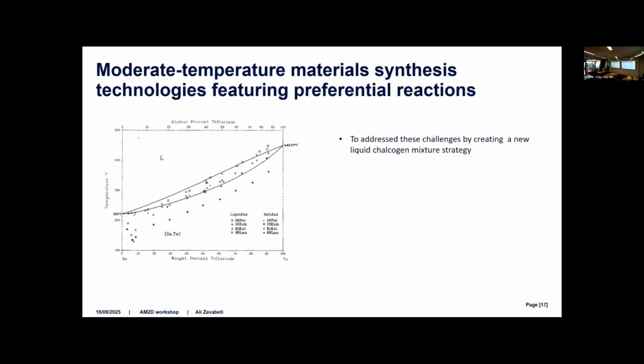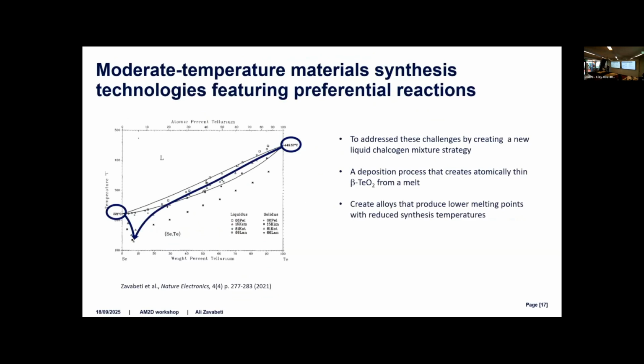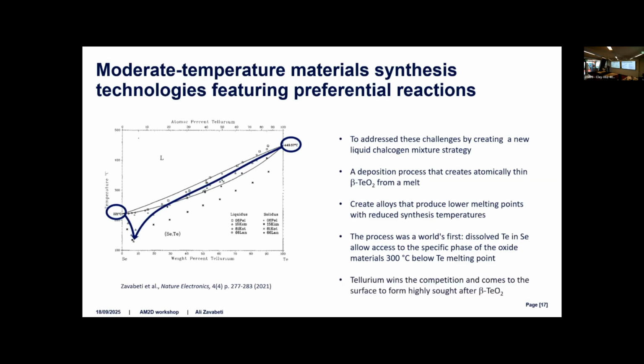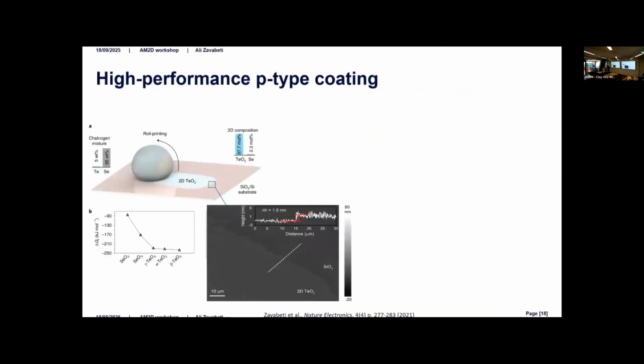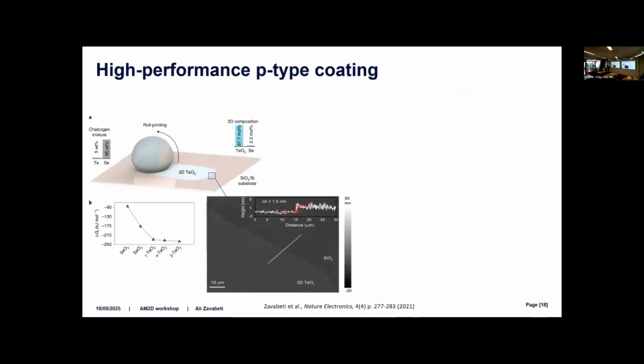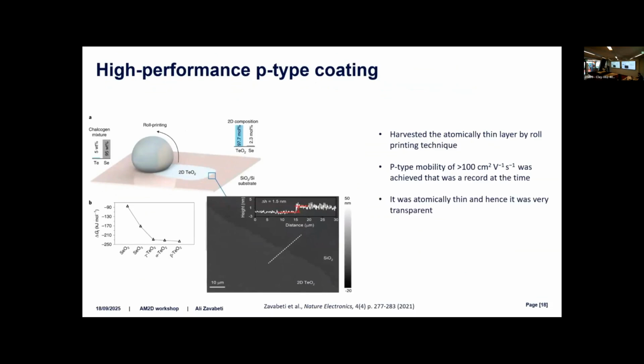So we use the same concept. We mixed in tellurium and selenium, and by doing that, we lowered the melting point. Tellurium melts at 450, and some phases of tellurium oxide are not achievable within that temperature. So we reduced the melting point and printed tellurium oxide in the beta phase, which is a high p-type mobility oxide. We made devices out of it. They are a wide bandgap, high mobility p-type coating. That's a SiO2 substrate, and this is a large area printed 2D beta tellurium oxide.